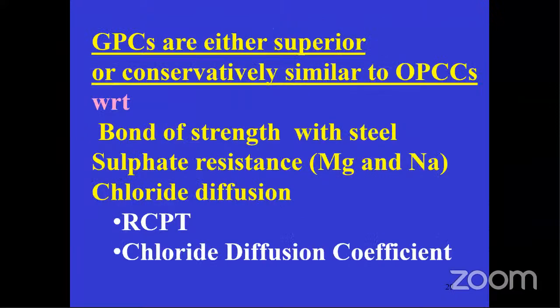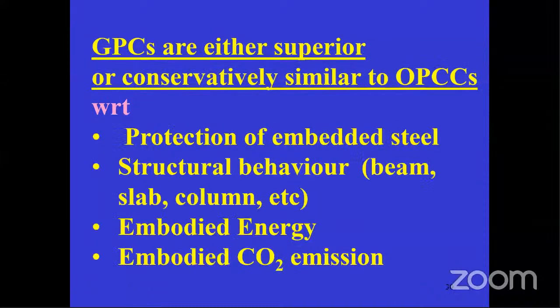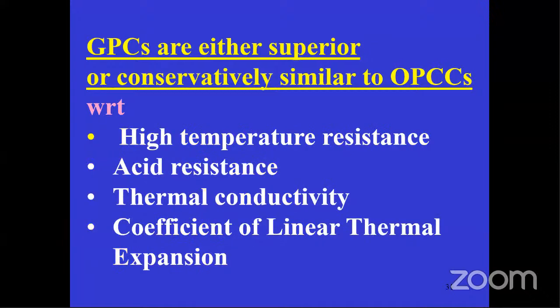Okay. Anyhow, the bond strength we have studied, sulfate resistance we have studied, magnesium and sodium both. Only sodium sulfate is not enough. And this is the most important: chloride diffusion coefficient you have studied. RCPT values may fail here, but the chloride diffusion coefficient will never fail to show that it is better. Okay. And we have done the work.